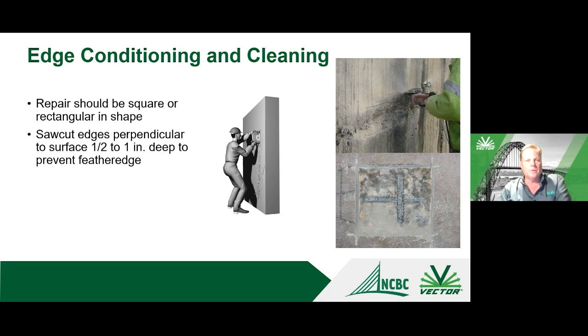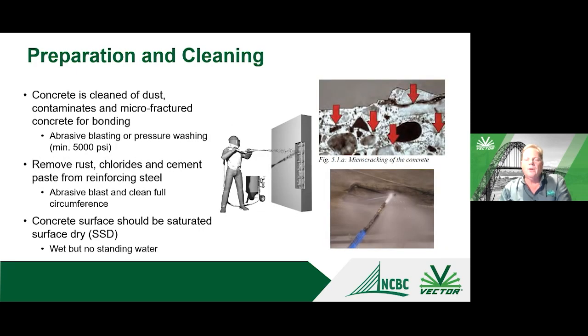Once again, surface preparation, saw cut edges. There's some good pictures of that being completed with just a hand grinder. One thing we also want to make sure we're doing is cleaning the concrete and removing any fragments or weak pieces in the substrate. And this is where you see this image here in the top right, where this is basically a slice into the substrate, which shows different micro cracking, or some people might call this bruising of the concrete down beneath.